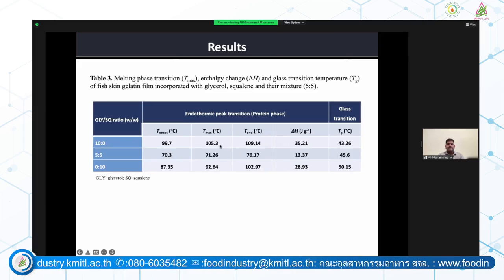And we could also see there was a good thermal behavior of the gelatin film, which indicated the different storage conditions. And we can see the Tmax, or T onset, is approximately near to the glycerol film. So this has not been affected significantly.